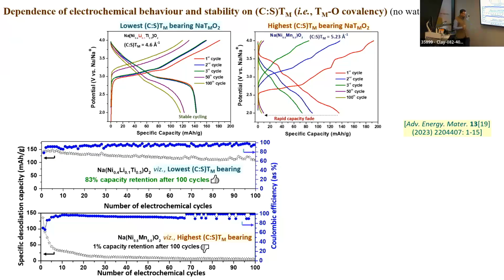So they're not exposed to air. Still, what we see is that the cathode material with the lowest charge to size ratio shows much better cyclic stability as compared to the material with the high charge to size ratio. Again, there has been no air or water exposure to any of them. Still, the low charge to size ratio is good not just for the air water stability, but also for the electrochemical cyclic stability. Why? We will see now.